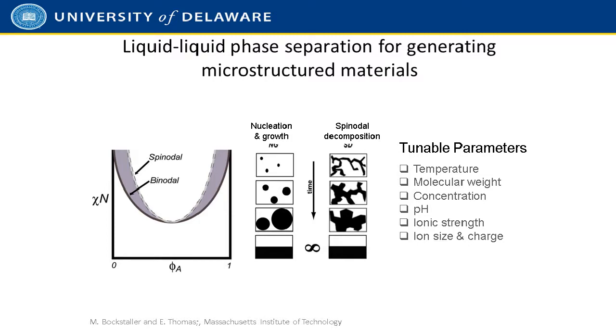If one is able to capture phase separation on the spinodal line, a different mechanism occurs, and in that mechanism there is a bicontinuous set of two phases generated that then matures into a sort of, you can imagine it looking like a vascular network, that one side of the gel would be continuously connected through a single phase to the other side of the gel. And if one can capture that phase separation in the earlier stages, you can capture this vascular-like network.